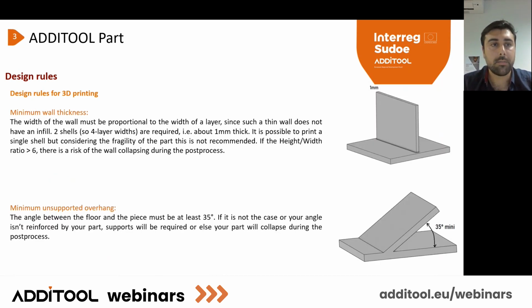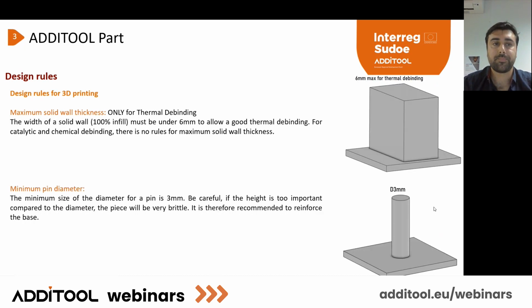So I can pass very briefly. Minimum wall thickness is about 1 millimeter, or the thickness of 1 or 2 weld beads. You also have, like a classical machine, an unsupported overhang; for the printing it is 35 degrees minimum. However, for the debinding, at 35 degrees you will need support to avoid collapse or deformation during your debinding process. So support is necessary to debind and to sinter.